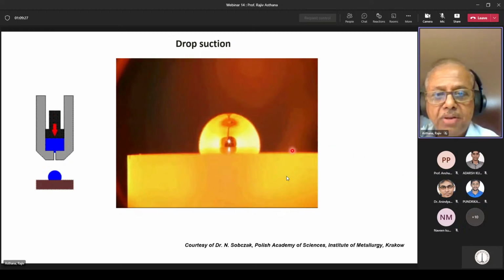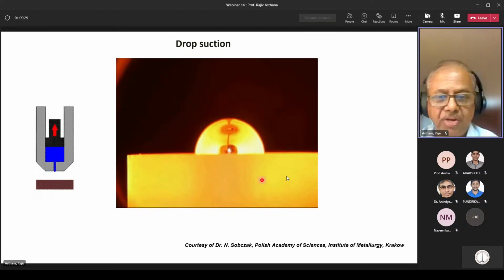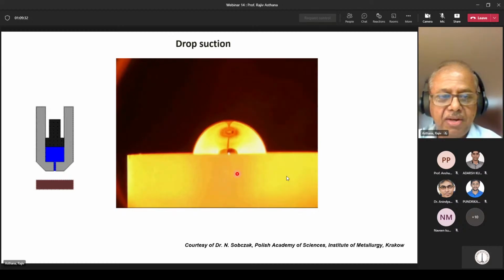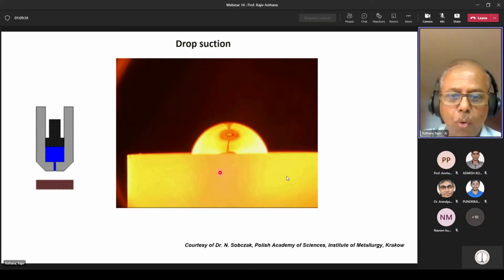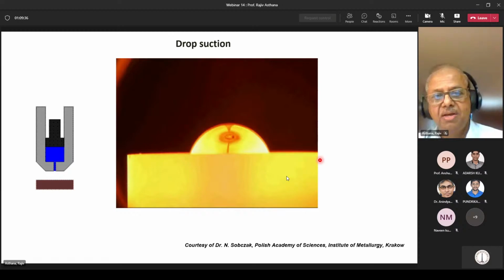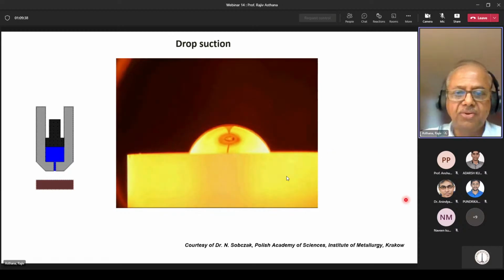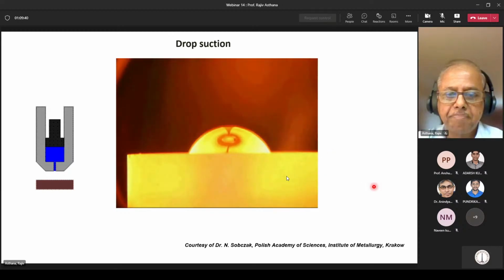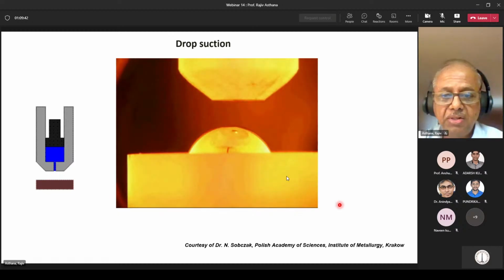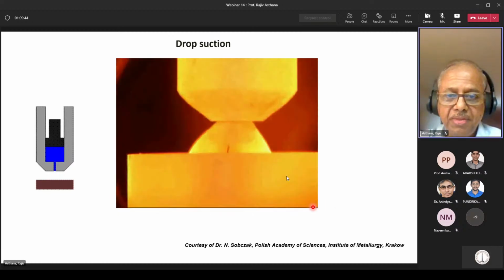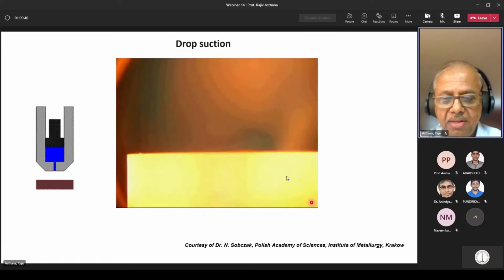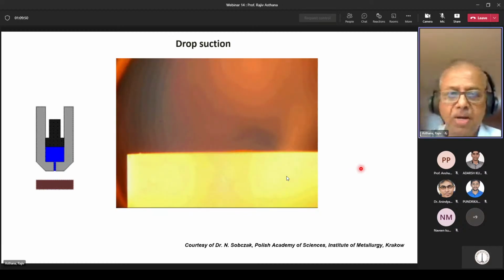One process we use is drop suction. You can actually lift the drop from the surface and open up the interface, and then study the interaction between the liquid and the solid. So after some time, you can lift the droplet, open up the surface here, cool it, and then see what kind of interactions took place as a function of time.